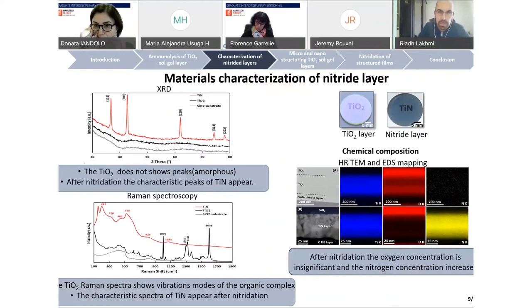When we make the titanium dioxide, we realize only a thermal treatment at low temperature, 110 degrees. Using this temperature, the titanium dioxide is not crystalline. It's amorphous. When we realize, for example, a thermal treatment of 500 degrees, we can see that the titanium dioxide is in the anatase phase. In this case, we have realized a low temperature thermal treatment, and the titanium dioxide is amorphous, because using this low temperature we can keep the photosensitive behavior of the sol-gel. So we want to use the same sequences to realize the non-structured titanium dioxide layers and the structured titanium dioxide layers. And for the structured layer, a low temperature thermal treatment is necessary.